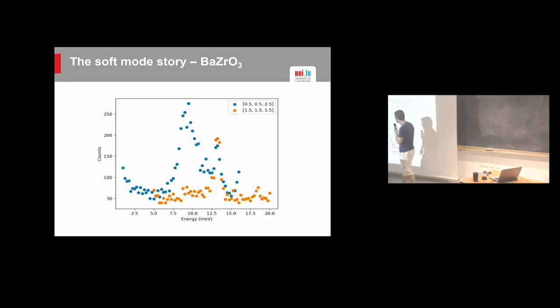This is an energy scan. And you have two modes in there, right? You have one that's here, that's quite sharp, and you have another one that's there and that's much broader. Essentially those two have been measured in different points in reciprocal space. And if you forget about symmetry and you measure around this yellow Bragg point, you don't see the mode you're interested in at all. So you have to move away. So this is just to mention that there are also those selection rules in neutron. And ideally you try to think about it before the experiment, if I'm being honest, but somehow we didn't see that one coming.